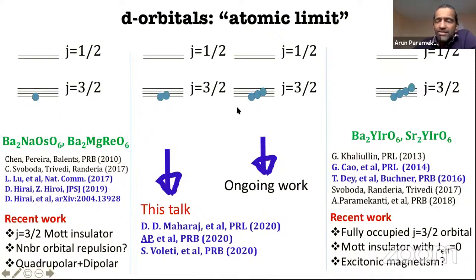So for all these fillings, you would have thought that there should be a single peak which corresponds to this energy difference between the J3 half and the J1 half. And clearly that's not true. Because once you put in interactions, of course, this level is not just 2 electrons here will actually split the degeneracy associated with how you put these electrons into these 4 levels.